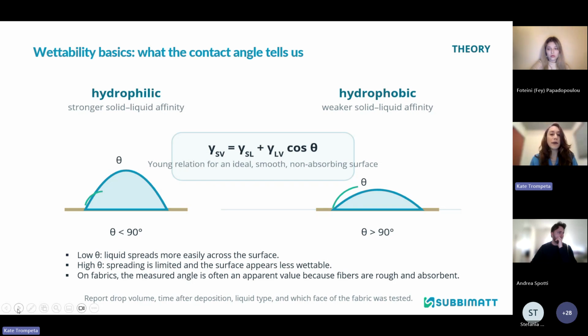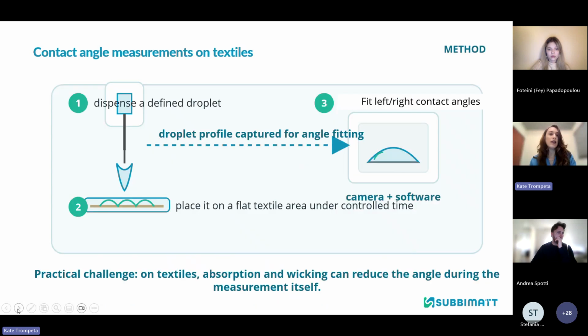So every time that we are making a measurement, we need to report the drop volume, the time after deposition, the liquid type, and which face of the fabric was tested. For you to understand the theta, it's actually the tangent at the triple point between the liquid, the solid surface, and the air. So how do we do this type of measurement, especially on textiles?